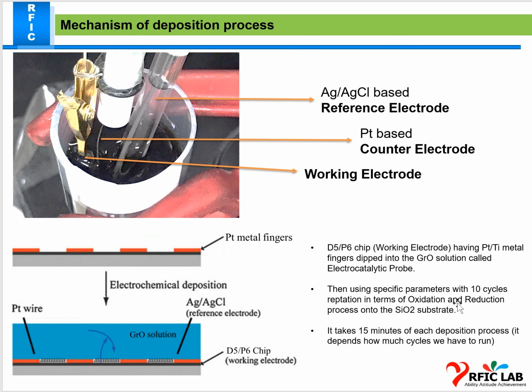So this is the main setup of this whole electrochemical mechanism. As I mentioned, our chip acts as a working electrode, the platinum wire is the counter electrode, and the AgCl based reference electrode. So these three electrodes are responsible for this whole process. The D5 chip with its metal fingers is dipped into the graphene solution, the electrocatalytic probe, and each deposition takes 15 minutes, but it depends on how many cycles we run. Previously I used 10 cycles, which takes 15 minutes, but now I'm considering 15 cycles, so it takes more, approximately 20 to 22 minutes for the deposition of each chip.